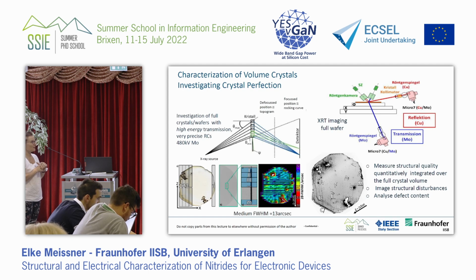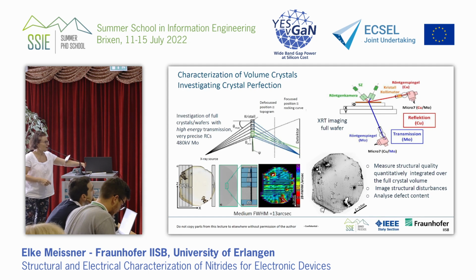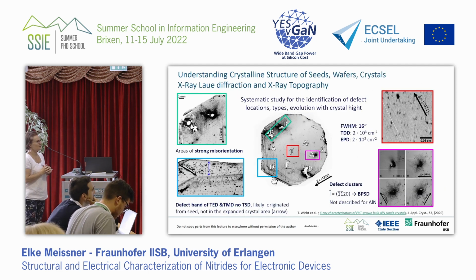So we say full width half max, if it's larger, it's less good quality, it contains, roughly speaking, more dislocations than a small value. It's not completely true, but first of all, you can consider it like this. So everywhere where you see blue areas, for example, the crystal is better compared to the places where you see the red areas. Now you want to know what is there at those places. And we take a picture now, which is a topograph, not a wide beam topography, but a monochromatic topography in that case, where we can map the structural quality of the whole crystal. And this is what you see, where we then also can mark some areas and investigate closer what had happened in such areas.